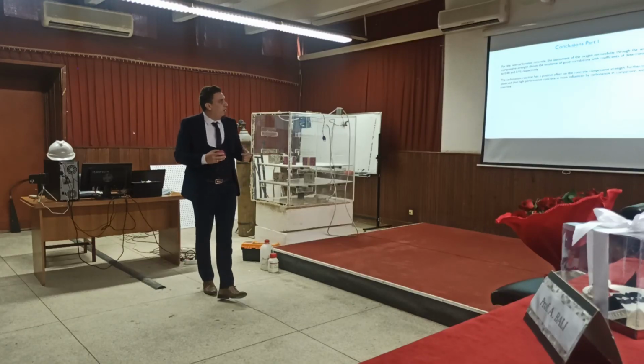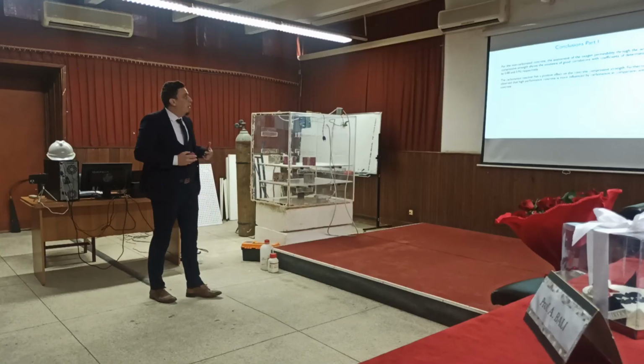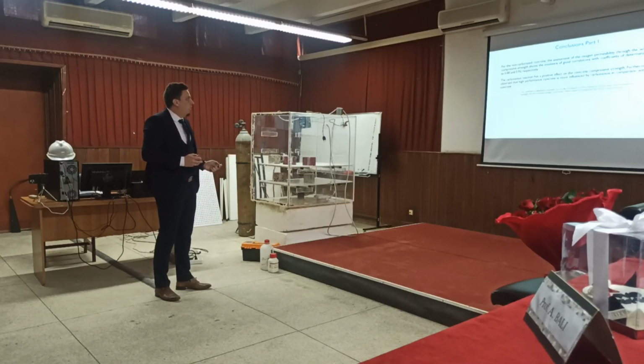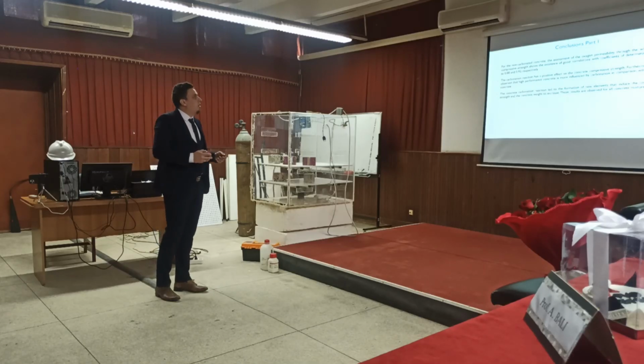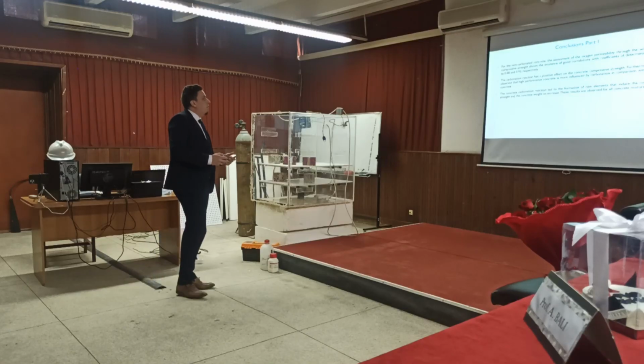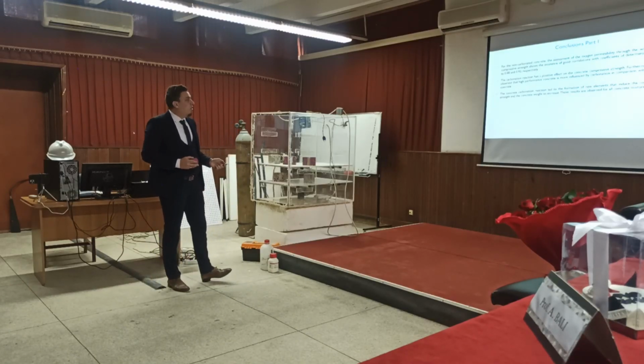Also, the carbonation reaction has a positive effect on the concrete compressive strength. Furthermore, it was observed that high-performance concrete is more influenced by carbonation in comparison with ordinary concrete. The concrete carbonation reaction led to the formation of a new element that caused the compressive strength and the concrete weight to increase. These results are observed for all concrete mixtures.